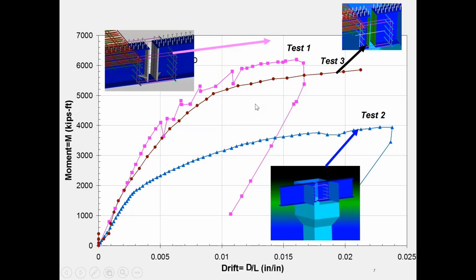This is a busy slide. What really, the essence of this slide is that saying that you need to have treatment at the end of the steel beam that's going to get embedded in the concrete diaphragm. You need to have an end plate, and you also need to have some mechanism to transfer the compression from one flange to another flange without going through the concrete. If you do that, then you will get a good behavior.